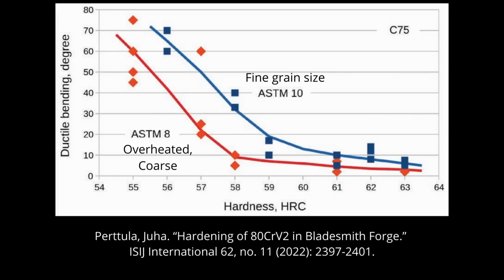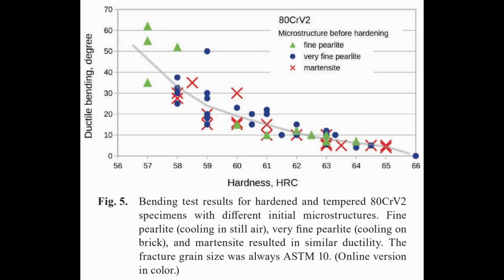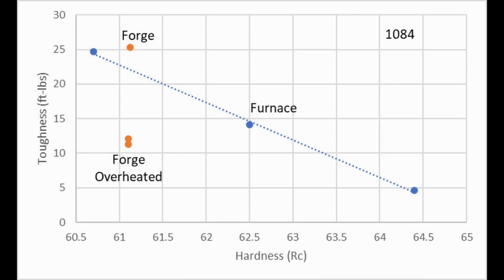Knife maker metallurgist Juha Pertula did an experiment with forge heat treating of 80CrV2 steel, and he found that when he held the steel beyond non-magnetic, it becomes non-magnetic when it transforms to austenite. He held the steel for 1 second beyond non-magnetic, and already the grain size had gone up and the toughness had gone down. When he used 80CrV2 with a small vanadium addition, that made the steel less sensitive to overheating. In my own experiments with forge heat treating, I also found 1084 steel, which is similar to 1075, to be very sensitive to overheating. It is very easy to heat it too hot. And this is very common in custom knives that are heat treated with a forge.